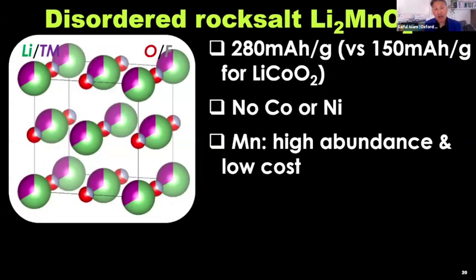So let me introduce you to disordered rock salt. I think all of you as chemists would know what a rock salt structure is. It's the stuff you sprinkle on your chips, on your pasta, in my case, before a tequila shot. So the rock salt structure is shown on the left, but with a difference. This is a disordered rock salt, where the cation site is both lithium and manganese. The anion site is both oxygen and fluoride. And the stoichiometry is at the top, Li2MnO2F.